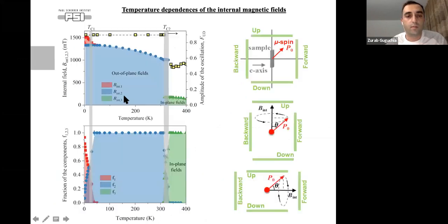And the difference between the internal fields means that if you now have fluctuations which are beyond the time window of muSR, then muSR would take a snapshot of the structure. So it's like a time-average structure. It seems that the time-average structure here is different from the real static structure here.